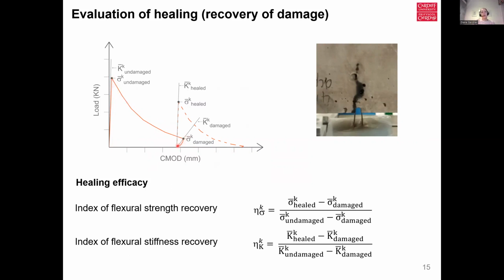We then unload, and then after a period of healing, depending on the healing agent, it could be hours in the case of cyanoacrylate, days, or it could be weeks in terms of sodium silicates. We then reload until we get to a peak load and a new crack formation, at which point we continue loading again, either to a predetermined crack width or until failure. And using the parameters that we see in the graph here, we can report not only flexural strength recovery, so that's recovery of the damaged portion of the original loading cycle, but we also have flexural stiffness recoveries that we can report.